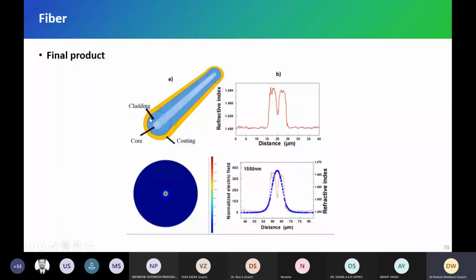So it has a refractive index profile like this. This is your cladding, this is the core, and inside there is a dip. This is very common. I expect some question on why there is a dip. In MCVD, the reason is that we are putting germanium dioxide and silicon dioxide, SiO2, in the core. This is the core region. When we are heating, some part of GeO2 becomes GeO. GeO2 is solid, GeO is gas, so it comes out. Germanium dioxide gives the higher refractive index, so as germanium is gone, you get lower refractive index, and so we get the dip. That is the reason for the dip inside the optical fiber.